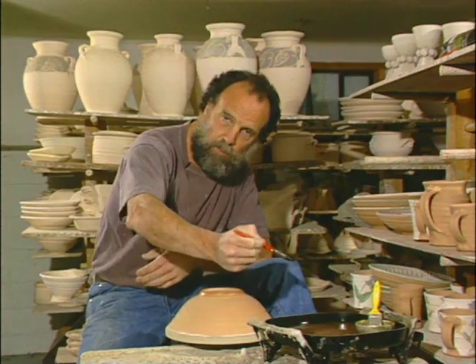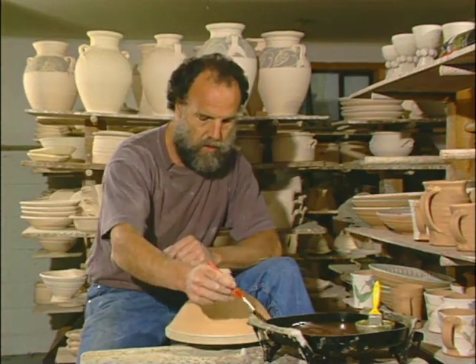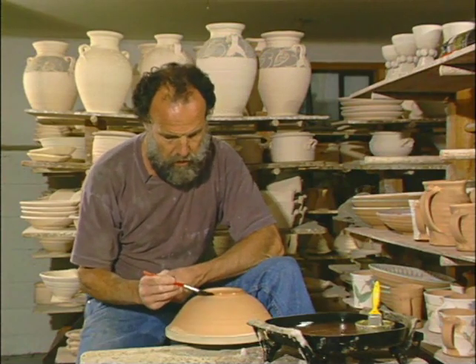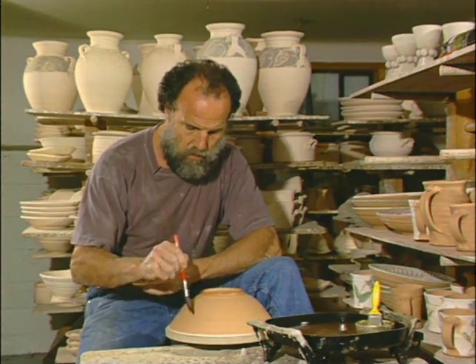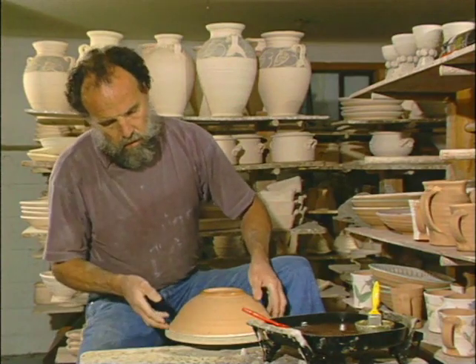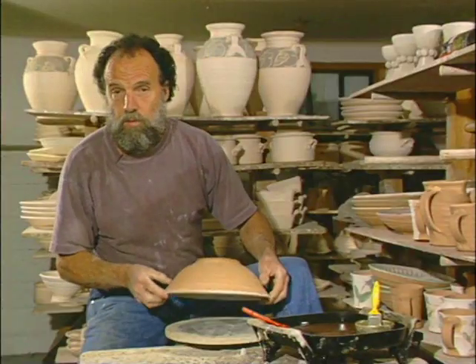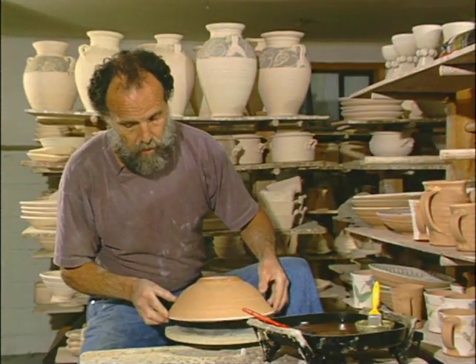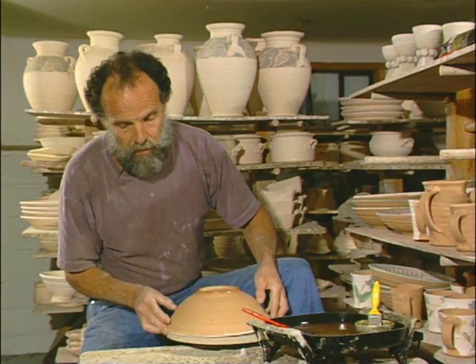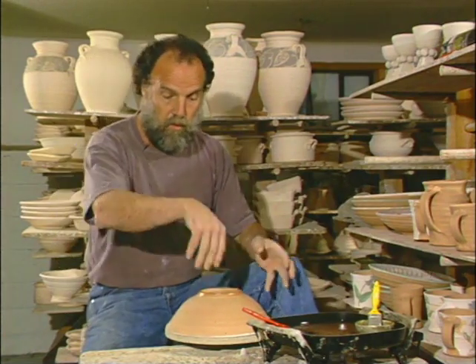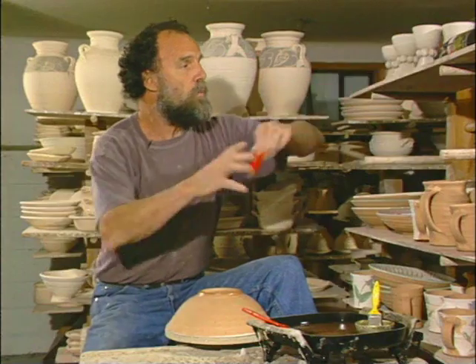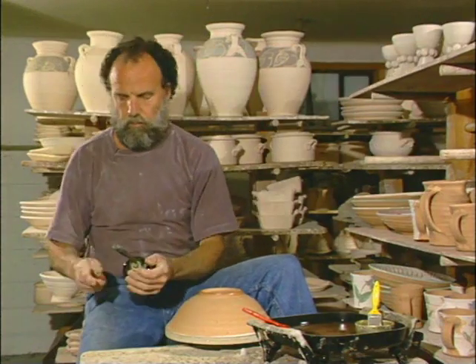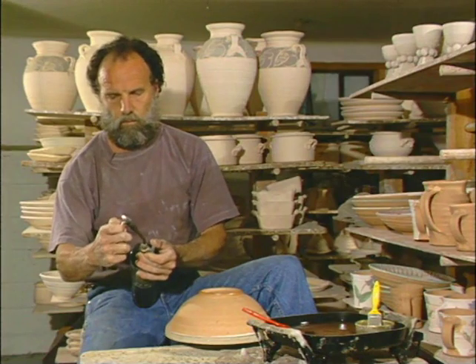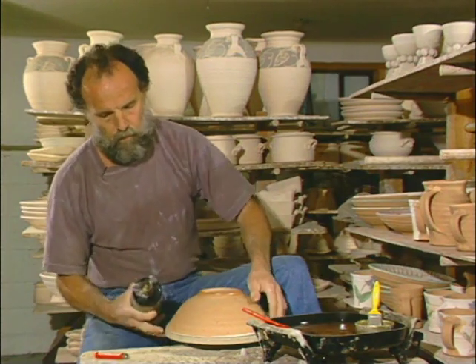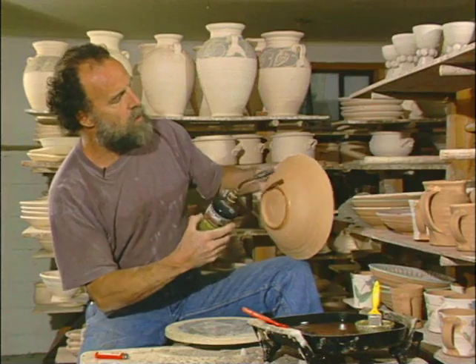If you tip the brush up as you move it away, you'll pour a blob of wax onto the pot. Let me see if I can do it and I can show you how maybe to remove it. Yeah, see, that'd be the result of an inadvertency with the wax. So the way to remove that, if some tragedy like that happens, is first of all to let it dry before you handle it. So don't pick it up and then tip it so that the dribbles run further, and then you can burn it off with a propane torch. Hold it away from you, and